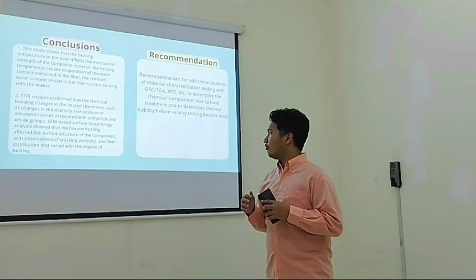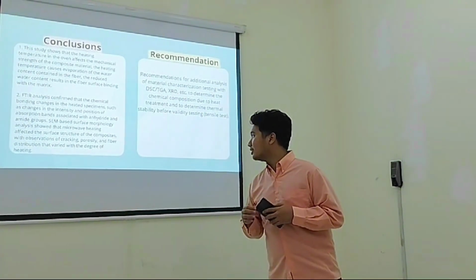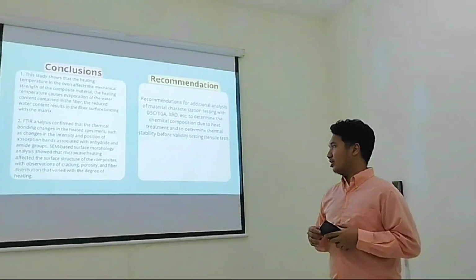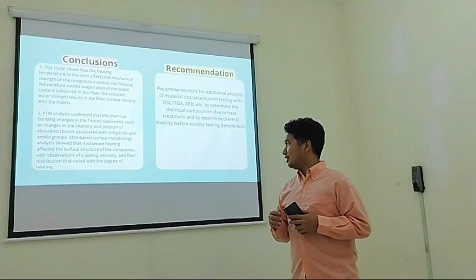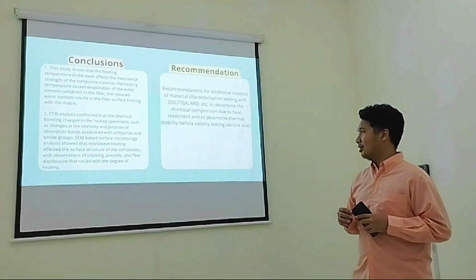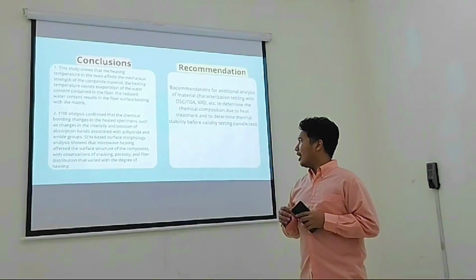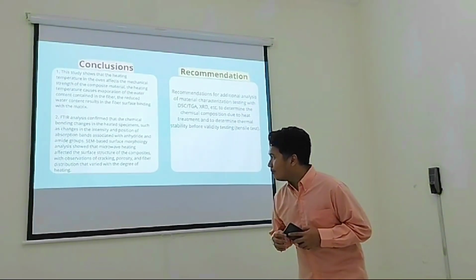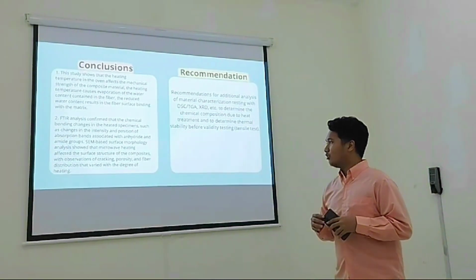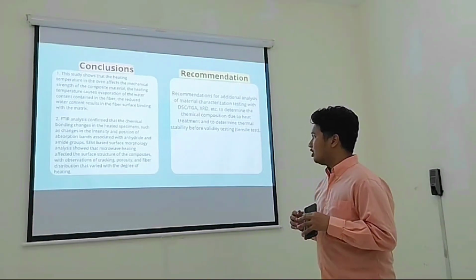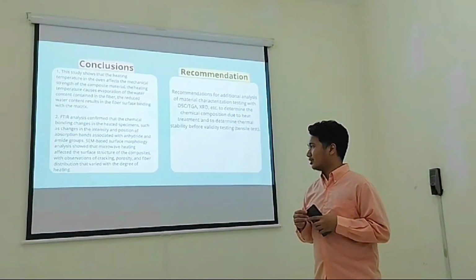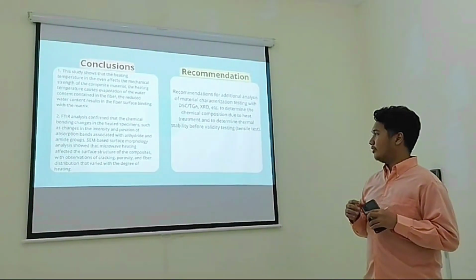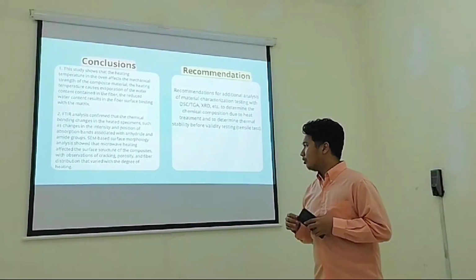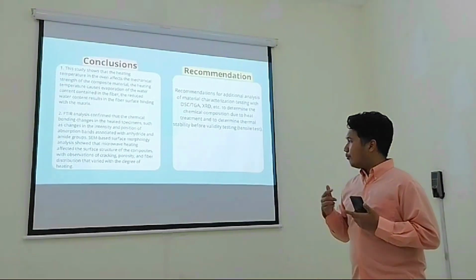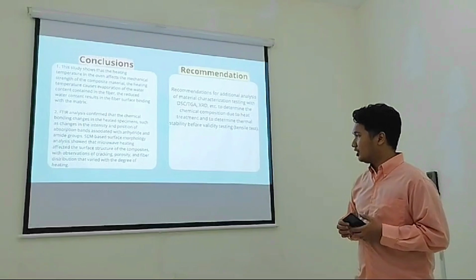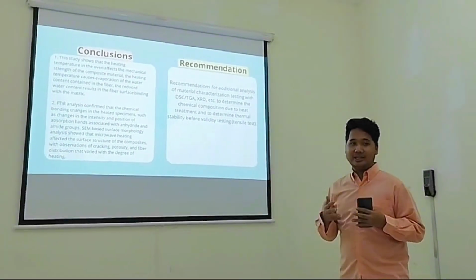FTIR analysis also confirmed the chemical bonding change in the heated specimen, such as changes in the intensity and position of the absorption band associated with anhydride and amide groups. SEM-based surface morphology analysis shows that microwave heating affected the surface structure of the composite, with observation of cracking, porosity, and fiber distribution that varied with the degree of heating.